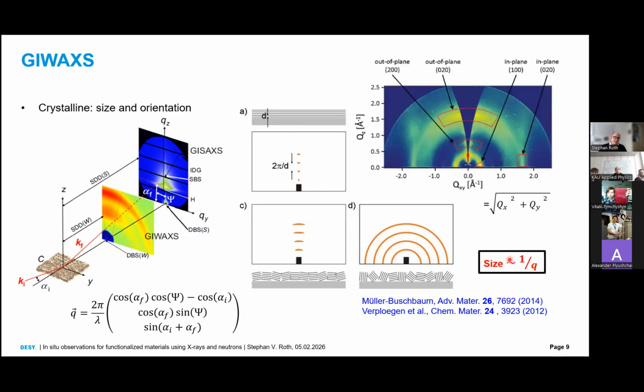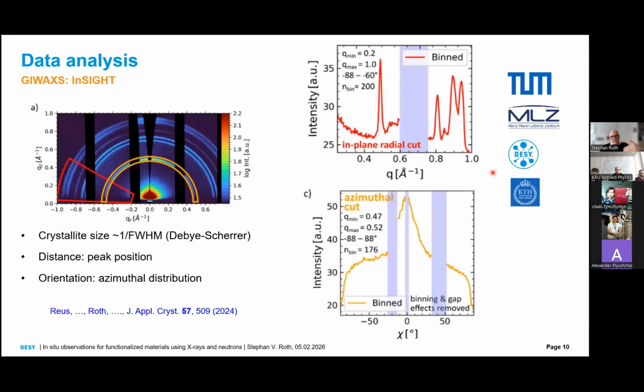And in order to fully analyze this, we have to map our two-dimensional flat detector onto the Ewald sphere, which gives rise to this pattern. And you see here an inaccessible range, which means that in GISAXS, a certain range in Q space is not accessible due to the symmetry breaking of the sample. Good. So this was the GISAXS, and now you see how we analyze this.